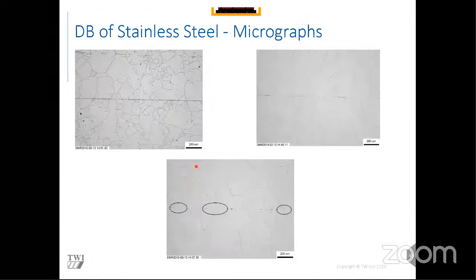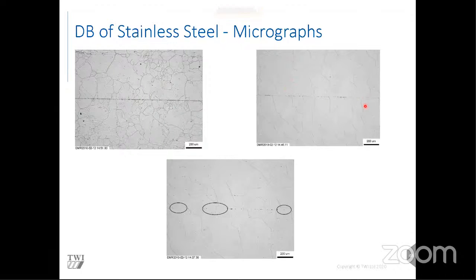Here are some micrographs of what we managed to diffusion bond. In the first set of parameters, you can see the bond line is very visible, with quite a few voids present, so that's not a very good joint. We modified the parameters and got something better, then refined further to get to this stage where the bond line has mostly disappeared.